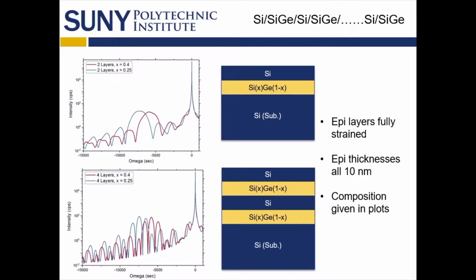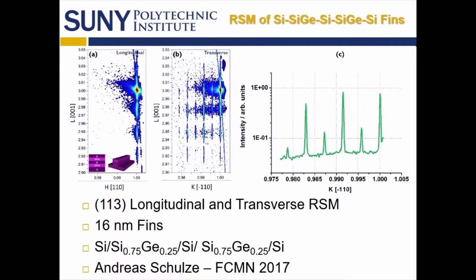You can see that in X-ray diffraction, and this is an omega-2theta scan, even though it just says omega here. If you increase the amount of germanium, there's a shift in this silicon germanium peak, which is the wider peak here in red, and it's easier to see versus the base silicon peak, which is labeled at 0 on the angular axis. If you put two layers in there, it gets more complicated. It's easy enough these days in the semiconductor industry to analyze this information. Nice software is available. Now let's make some fins out of that.